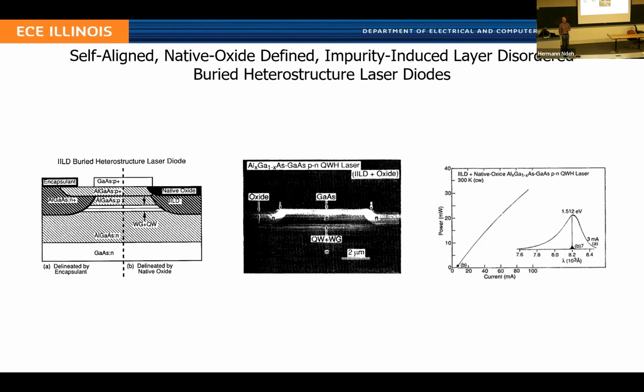With that new materials technology, we looked at what we could do to make better devices. One of the first things we did was look at making improved lasers where we were disordering. We would diffuse silicon into the laser and intermix the material and form a high gap PN junction, as well as an optical lateral waveguide from the intermixing. But the problem is conventional devices had to have multiple alignments, to align the diffusion and then to align isolation junctions on top of it. Because the native oxide was selective to the aluminum, we were able to make a self-aligned process. With a single diffusion step and a subsequent oxidation step, we made high performance buried heterostructure single mode laser diodes that were just as good as ones that required roughly twice the processing.